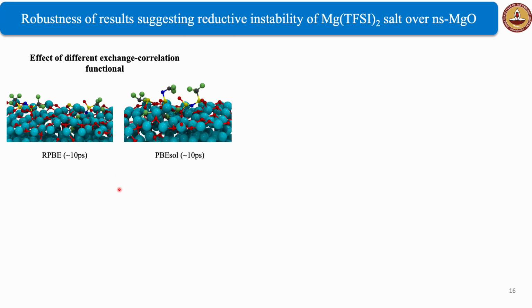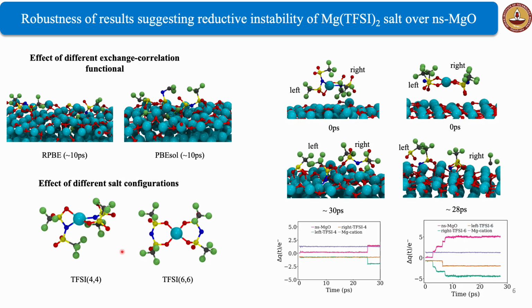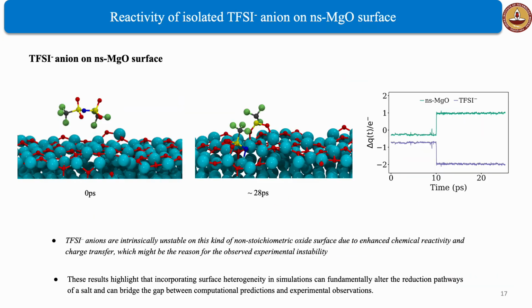To check the robustness of our results, we also checked the effect of different exchange-correlation functionals and the effect of different salt configurations, that is TFSI 4-4, where both the TFSI anions form a 4-membered ring, and TFSI 6-6, where both the TFSI anions form a 6-membered ring with the magnesium cation. In these cases also we observed similar findings, indicating the robustness of our results. We also checked the reactivity of isolated TFSI anions on the ns-MgO surface, and we found that the TFSI anions are intrinsically unstable on this kind of non-stoichiometric oxide surface due to enhanced chemical reactivity and charge transfer, which might be the reason for the observed experimental instability.